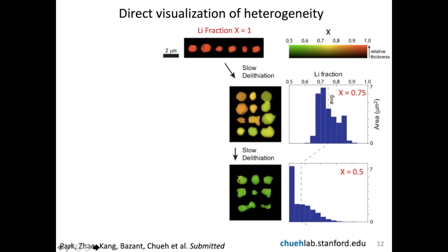but also the local behavior. So according to the diffusion picture, if you were to take the lithium out of the material, you have phase separation. If you let the material equilibrate, almost all the particles would have the same lithium composition from the relaxation and the equilibration of lithium within the particle. So if you don't let lithium exchange between the particles after relaxation, this is what you will see. And indeed, this is what you see when you charge slowly and discharge slowly. The histogram here basically shows you have some spread in the lithium composition represented by the colors here, and everything behaves correctly as you would expect.